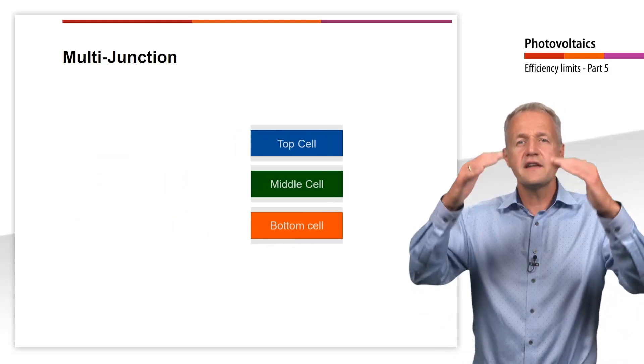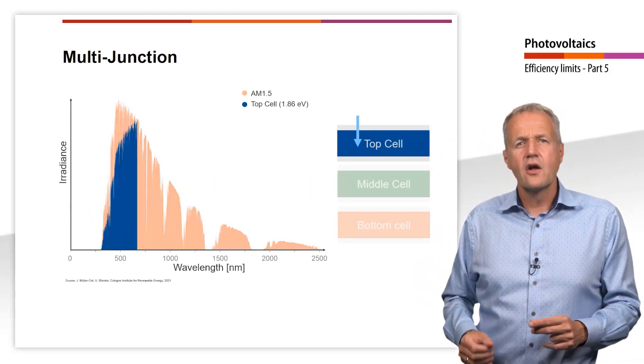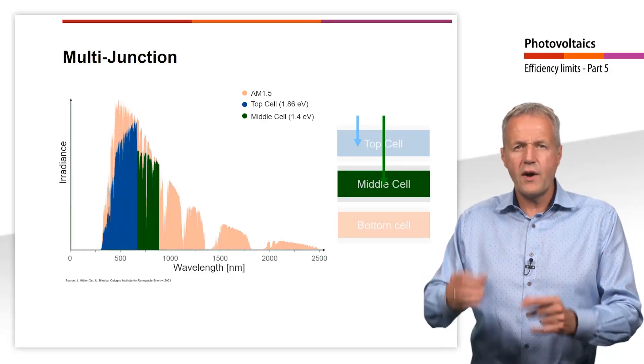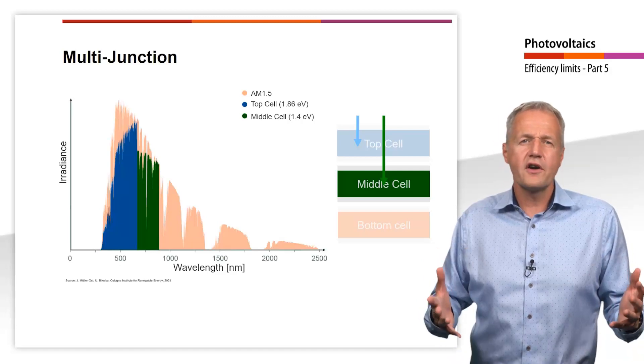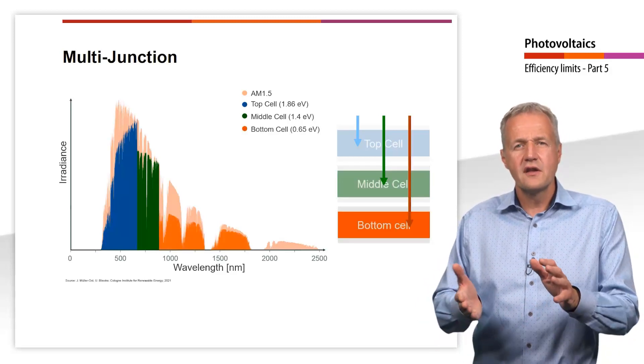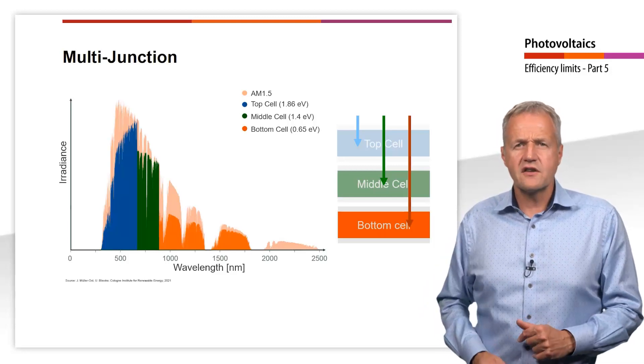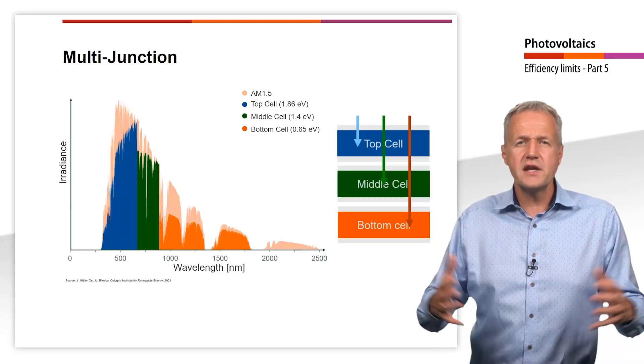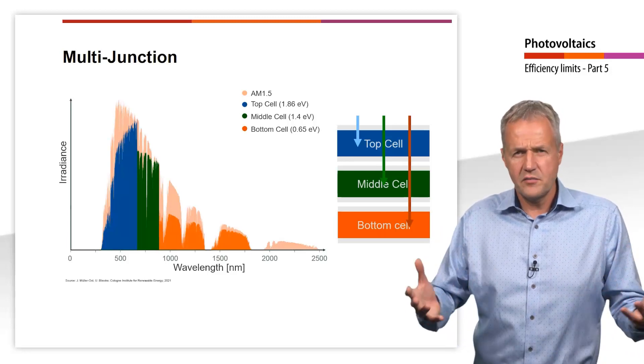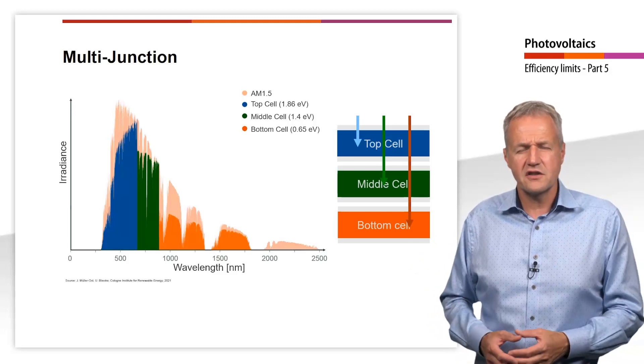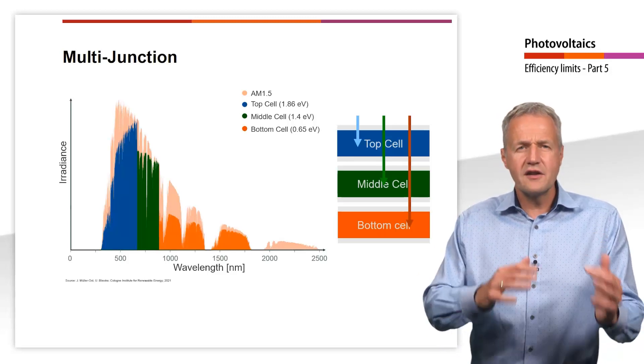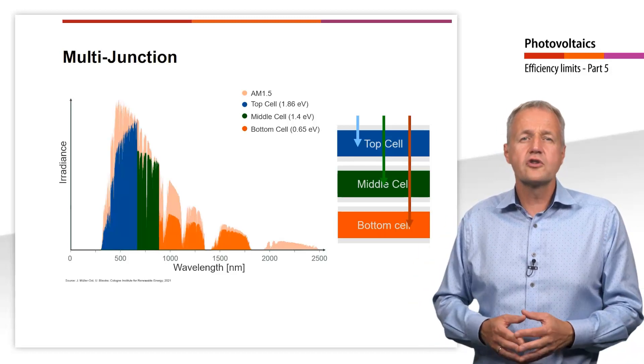The top cell has the highest band gap and absorbs mainly short wavelength light. Long wavelength light is transmitted and hits the middle cell, which has a somewhat smaller band gap. It absorbs light in a medium wavelength range — more specifically a spectral range around 750 nm in the red and near infrared region. The lowest cell has the smallest band gap and absorbs in the long wavelength range. With such a structure, the efficiency can be increased significantly. For example, the peak value for a triple solar cell is currently 37.9%. However, most multiple solar cells are very expensive and are therefore mainly used for space applications. This might change in the future as cheaper large band gap semiconductors like perovskites, which can be combined with silicon to a tandem device, are being developed, and as problems in terms of long-term stability are being solved.